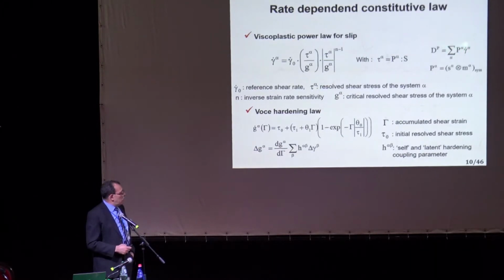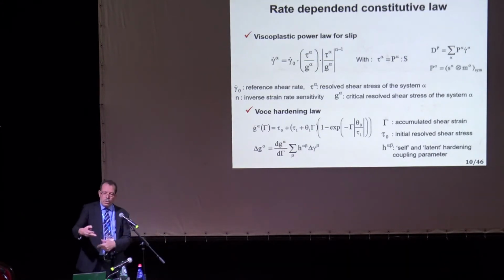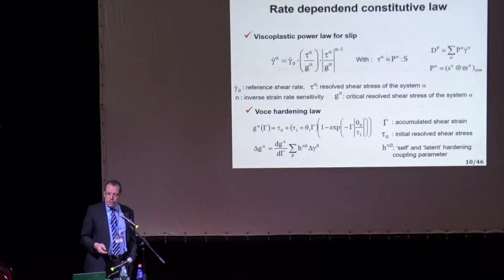The sum of these weighted by the P alpha, which is the symmetric part of the Schmid factor, which is in fact the cosine directors. So that gives you your plastic strain rate tensor. And in this law here, the shear rate is related to the shear stress on the given slip system alpha, and of course it depends on the resistance to shearing, or the critical resolved shear stress. And this resistance to shearing, of course, evolves with deformation. That's what we call strain hardening. So we have to apply a hardening law for the evolution of this resistance.